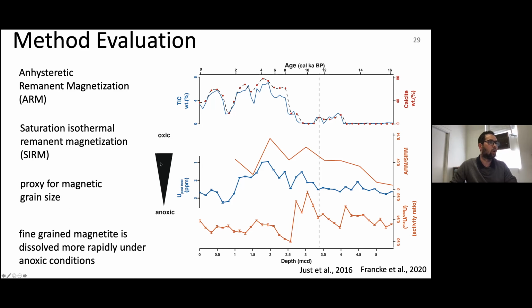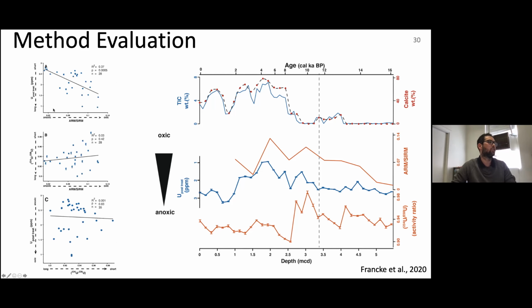But we see this trend to more oxic conditions from the late glacial into the early Holocene, and we kind of see a correspondence to our uranium concentrations, but we don't see any correspondence to our activity ratios. And we have some scatter plots here, again, to test any statistical significance between our uranium concentration and the redox proxy, and we did find some sort of correspondence with more oxic conditions corresponding to lower uranium concentrations, which is indeed what you would expect, since uranium is a bit more mobile in oxic conditions. But that seemingly has no control. These redox conditions obviously have statistically no control on the activity ratios that we measured in the sediments of Lake Ohrid. And we also find no statistical correlation between uranium concentration and the activity ratio.